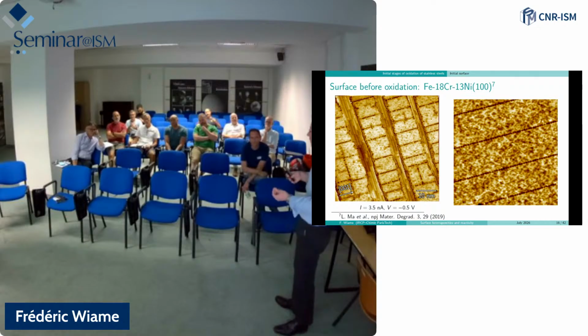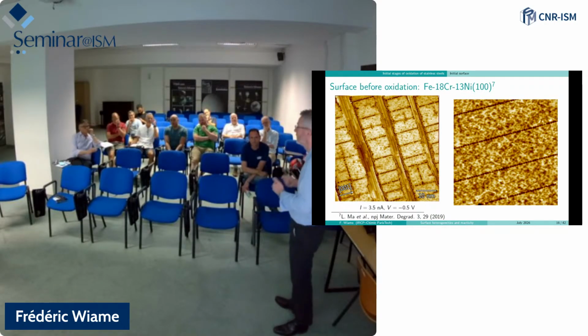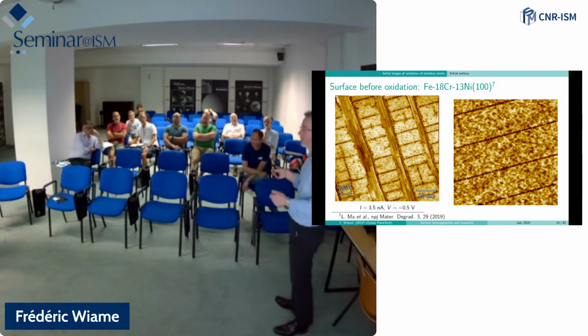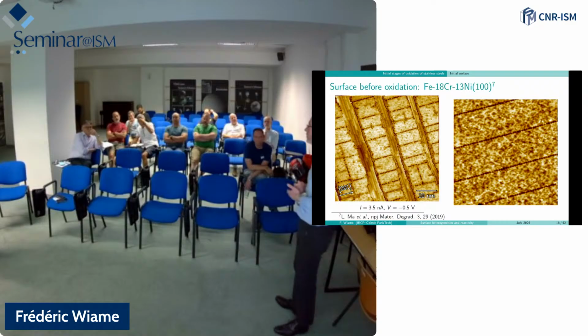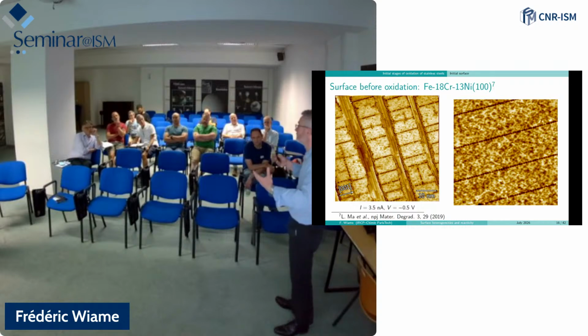The problem is slightly different from having stainless steel, because with stainless steel, if you scratch the surface, you still have chromium in the bulk, and so you will reform some chromium oxide. If it's just a deposit and you have a scratch, for example in the chromated bumper on your car, before it was like this, they just had normal steel and deposited chromium. Then if you have a scratch, it will corrode, or sometimes it can even corrode below the chromium layer, and then you see that the chromium just peels off. So yes, there are possibilities. There are other solutions to corrosion, which is inhibition of the surface. The problem with inhibitors of corrosion is that when you remove them, you still have corrosion. While in the case of stainless steel, if you remove the oxide layer, you will reform the oxide layer.